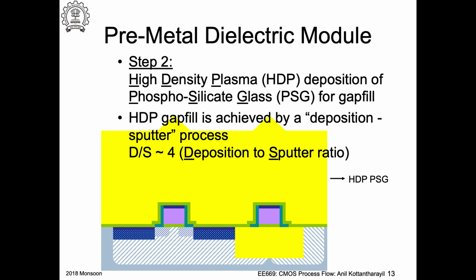And then you do this high density plasma oxide. You are going to use this deposition and sputter process, with a deposition to sputter ratio. One typical number is given there, 4. But again, as I mentioned, all these numbers could depend on the technology node, and different manufacturing lines may use different processes. So you get this, shown in yellow color, the HDP phosphosilicate glass. And then you're going to flatten it out by using CMP.